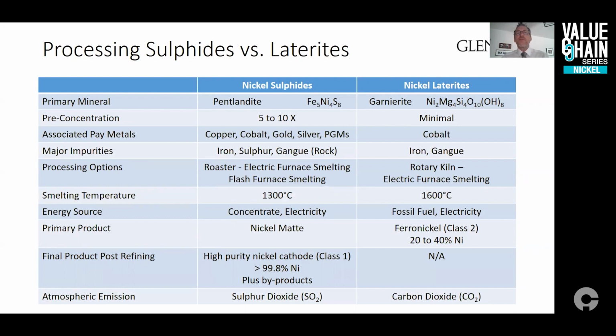The product of nickel sulfide smelting is low iron nickel sulfide matte. The matte undergoes refining, where the remaining iron and sulfur are removed and byproducts are recovered. High purity class 1 nickel cathode is the typical end product. The product of nickel laterite smelting is class 2 ferronickel, containing typically 20 to 40% nickel with iron as mostly the balance, which is sold directly to stainless steel producers.